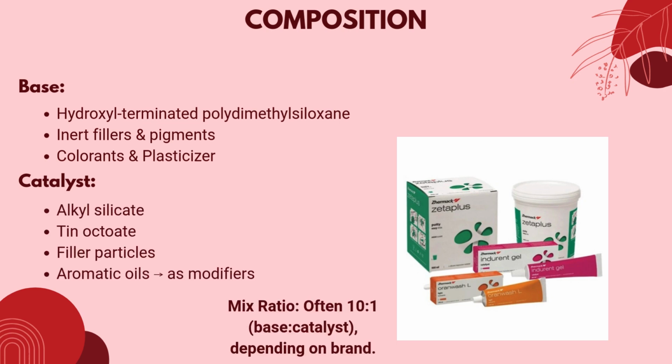The curing of this material involves a reaction of tri- and tetrafunctional alkyl silicates in the presence of stannous octoate as a catalyst, present in a catalyst paste. It also contains some filler particles and aromatic oils as modifiers. The mixing ratio is 10:1, 10 parts base and 1 part catalyst.